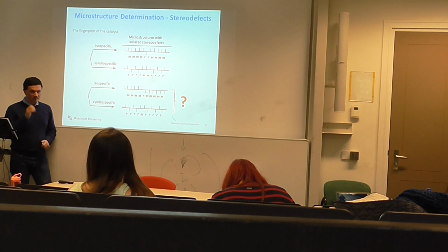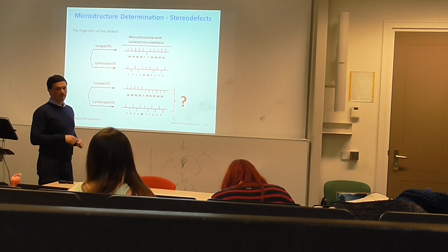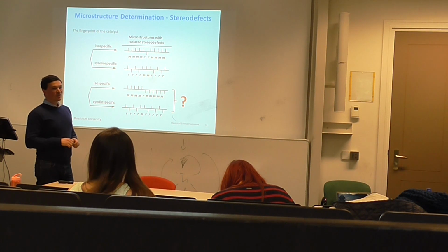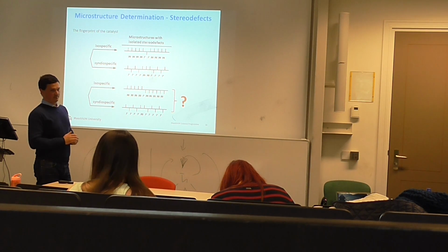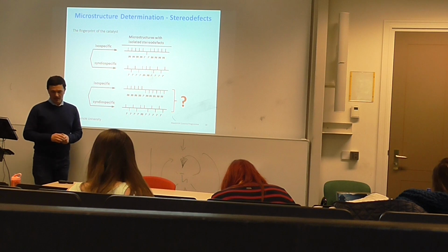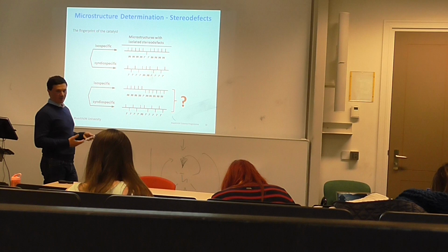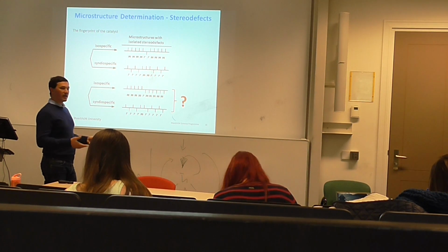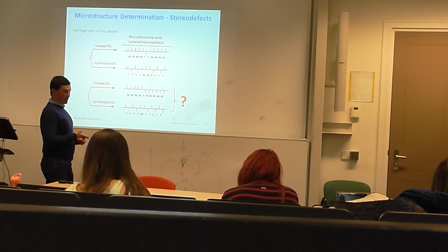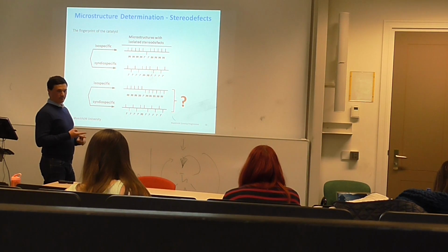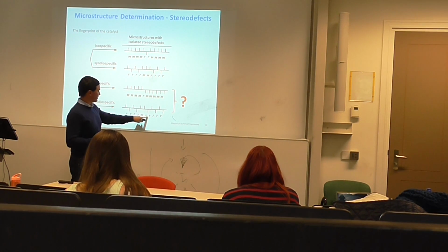Does that mean that the catalyst has no influence at all in this case? It's just the chain? Not on the stereo selectivity. Okay? So you can understand these things by looking at the chain, so at the polymer. So you understand the source of stereo regularity, if it's chain controlled or site controlled stereo selectivity, by looking at these strings.